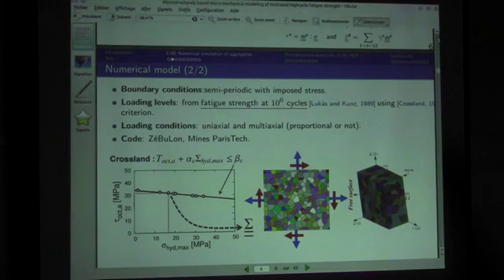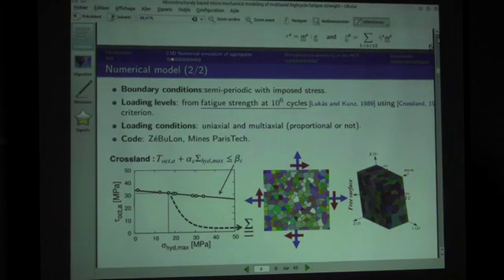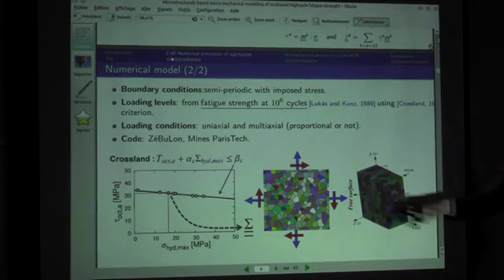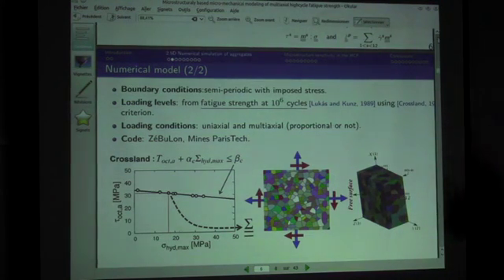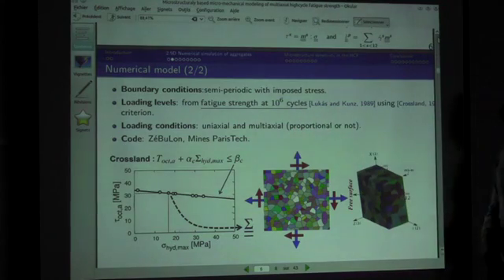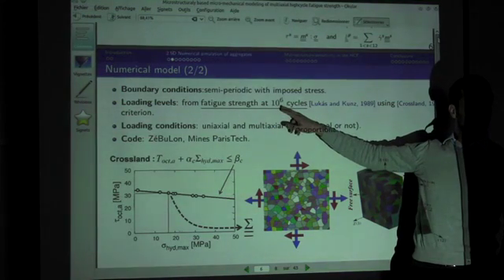So once we have those microstructures, what we have to do is to compute them and to choose the load levels. What we have been doing is identifying, from a given criterion, the different macroscopic stress states that we have to apply on our aggregates to have an equivalent fatigue life with respect to the criterion. For example, for copper, we use some data from Lukas and Kunz, at fatigue strength at 10 to the 6 cycles. So we're dealing with high cycle fatigue life, 10 to the 6.